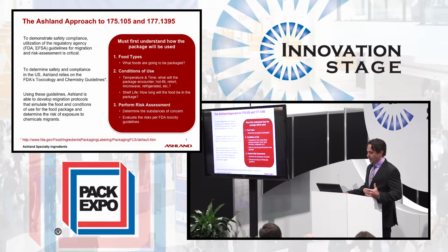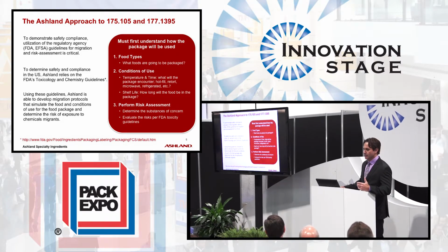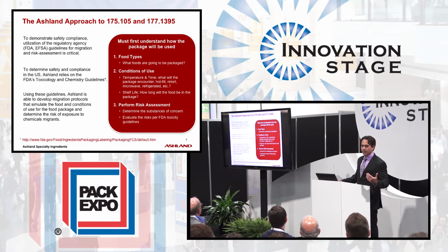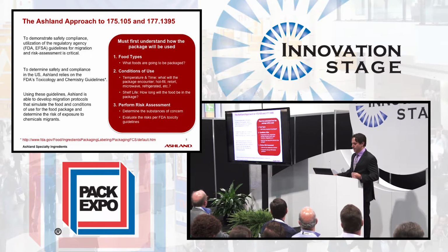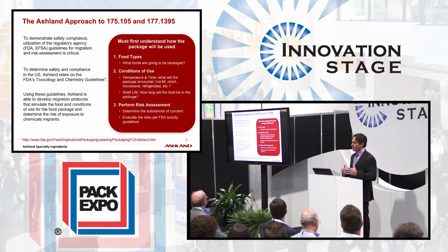You really need to understand the package. What type of food is going into it? The type of food can greatly determine how a product will migrate. Also, what are the conditions? The higher the temperature, the more migration you're going to see. How long is it going to sit on the shelf? Again, that will enhance migration. So you have migration. What does it mean? What's coming out? You have to perform a risk assessment on those chemicals that have migrated to determine if they are safe at that dietary level that you anticipate.